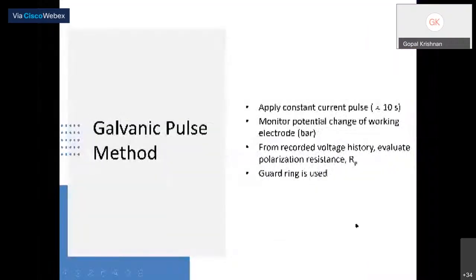So when you are doing this, even within 10 seconds, you can apply the galvanostatic pulse into the structures. We are able to get it, and it also gives the electrode. We need to probe with the electrode in a different, we can say, grid format. From the recorded voltage history, we can evaluate the polarization resistance RP. The guard ring which I showed is used to do the grid mapping.